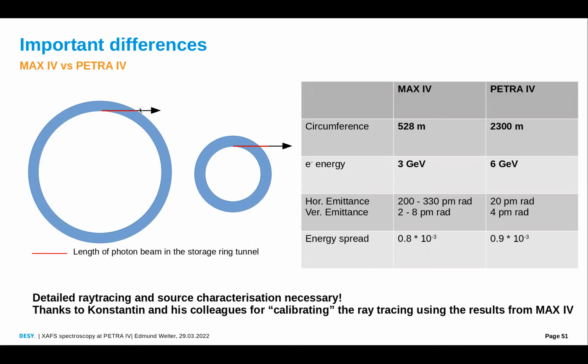So we can place our first optics. Well, we certainly have to place it in the storage ring tunnel, which is a problem with the technical groups. They don't like it very much. This is simply caused by the larger circumference. The second problem is we have 6 GeV and not 3 GeV. So all these effects will be more pronounced because we need to use weaker wigglers, which have more undulator-like behavior. And we have similar or comparable emittance, but at much higher energy.